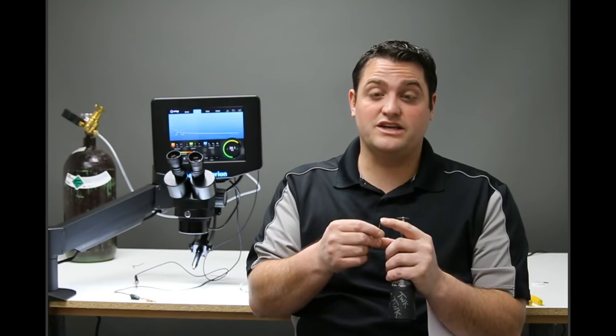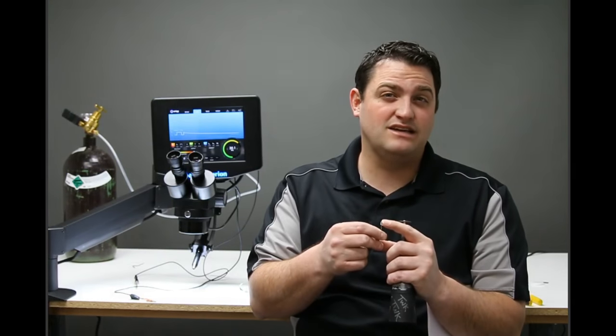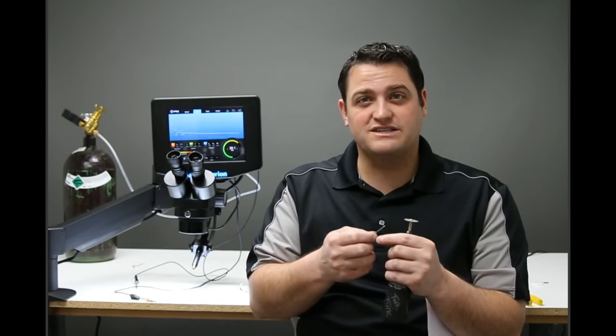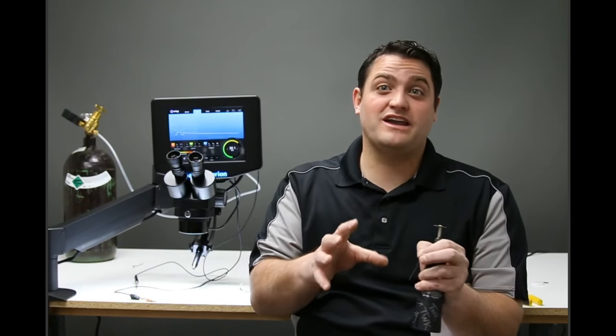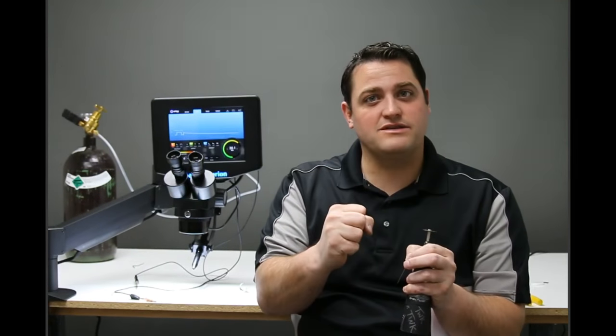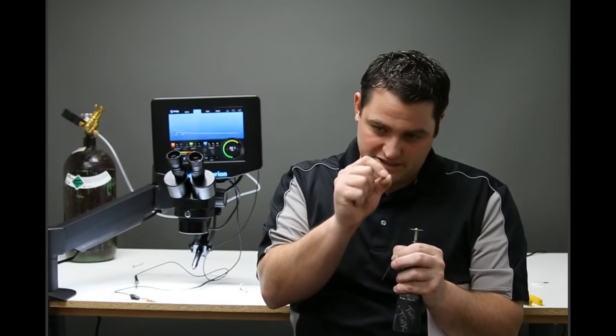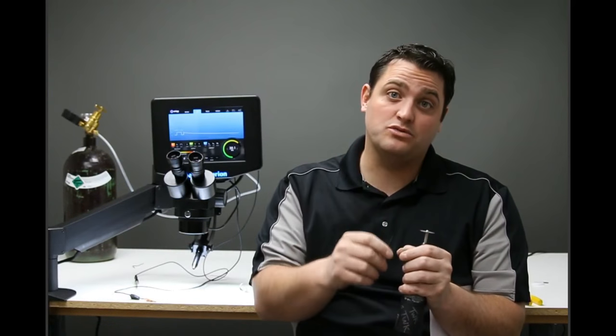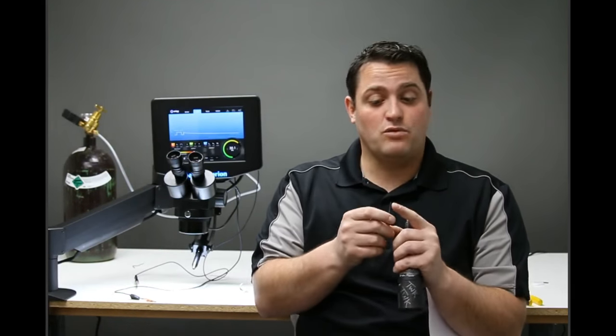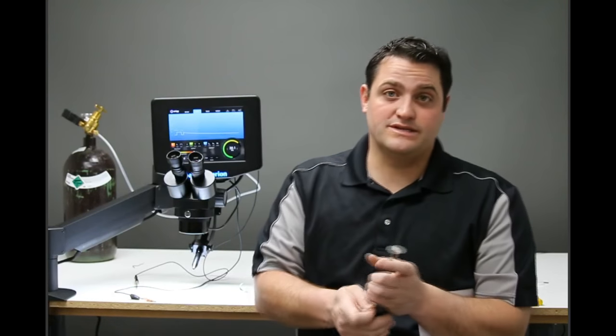If we have it really truncated at like 80%, and then we're trying to weld something really fine, it's going to spread out, and it'll tend to melt around the piece more than very specifically where you want it. So the more precise you want to be, the sharper your electrode should be, with silver specifically.